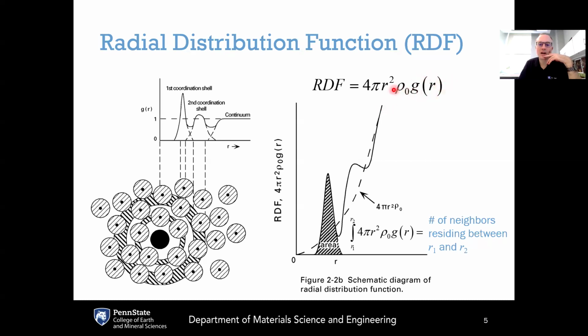But this gets multiplied by a parabola. It gets multiplied by 4 pi r squared rho 0. So multiplying by this parabola, shown by the dashed line, instead of having the peaks and valleys oscillating around a constant 1, they end up oscillating around that parabola. Then if you integrate this radial distribution function between two different r values, say r1 and r2, the area of that integral is going to give you the number of neighbors residing between r1 and r2. So integrating the radial distribution function is like counting the number of neighbors. For example, for this shell here, let's suppose that we got this first nearest neighbor shell.